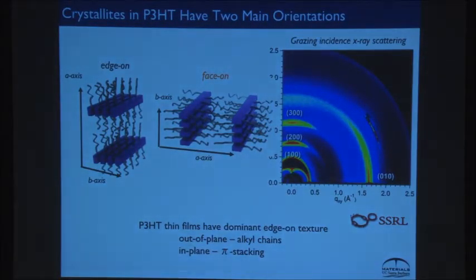Just to give you a sense of this, if I take semiconducting polymers, a classic one is poly-3-hexylthiophene, and I do an experiment called grazing incidence diffraction, where I take a thin film and I scatter X-rays off of it, and I detect them with a plate, what I'll see is a number of diffraction peaks here. If I had a powder, I'd just see rings. I don't see rings. What I see are peaks along this axis and some peaks along this axis.